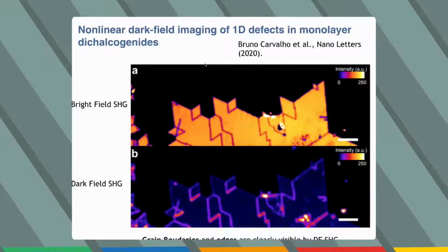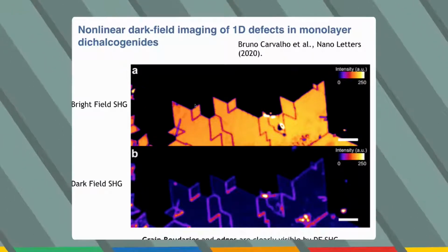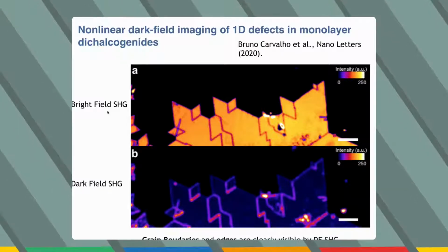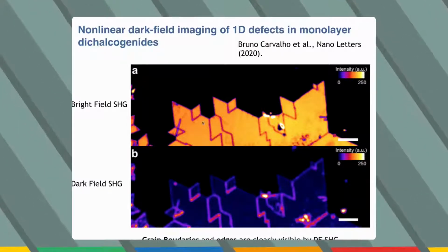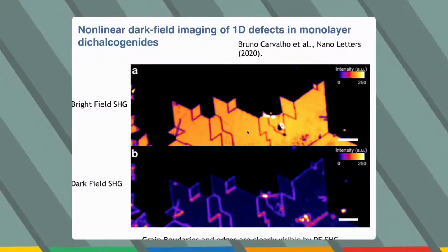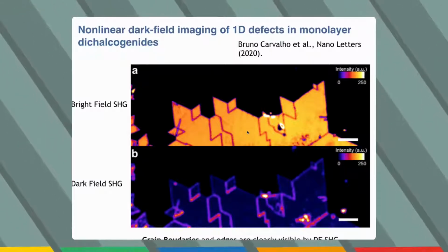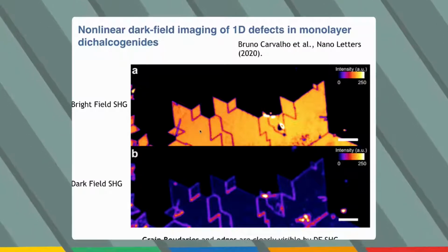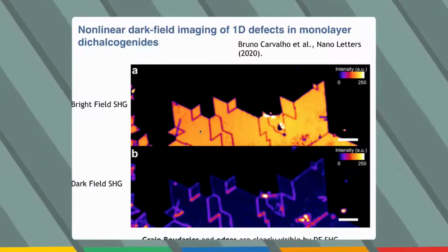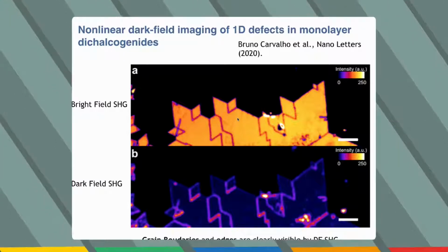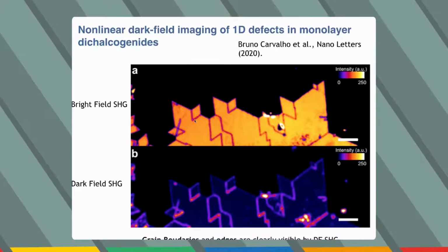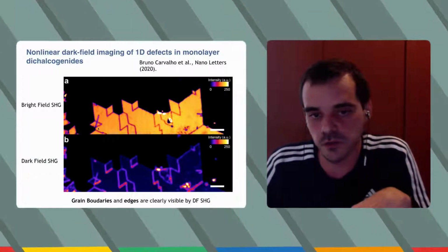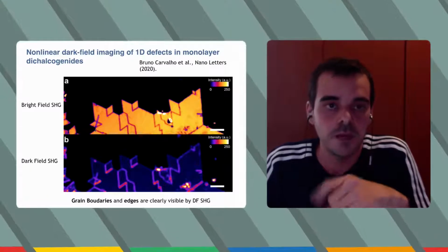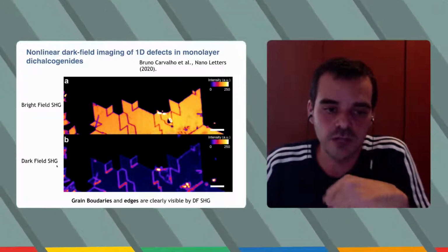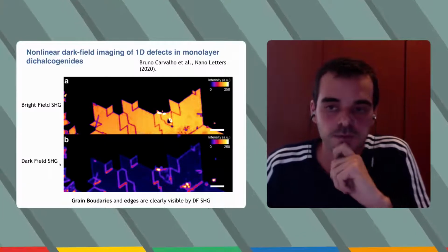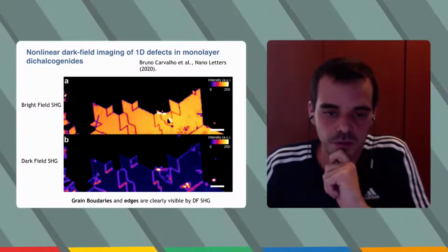So here I'm showing that we can also probe defects. This is a second harmonic image, what we call a bright field second harmonic image. This is a sample that was grown by chemical vapor deposition. This type of sample generates a lot of grain boundaries, so we have different crystal orientations. So we have this type of disorder, and between the crystals we have a grain boundary here that doesn't generate second harmonic. But then if you do what we call a dark field second harmonic, for more details, please look at this paper, or we can talk later.